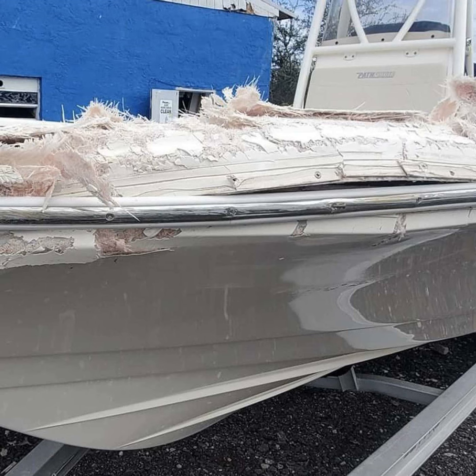And you can break out the old glass man's welder, as I like to call it, the hot glue gun, and just put some very minimal dabs of hot glue in an area where you're not going to glass. Try to get it on that 1-inch surface where the backing patch is going to touch over the existing glass from the inside, and put a few dabs of hot glue. And then very gently with that string, you pull it tight. Don't pull it too tight, otherwise you're going to dish the center upwards and make it too thin right there. But you're basically just trying to give yourself a work surface that you can build some glass to.